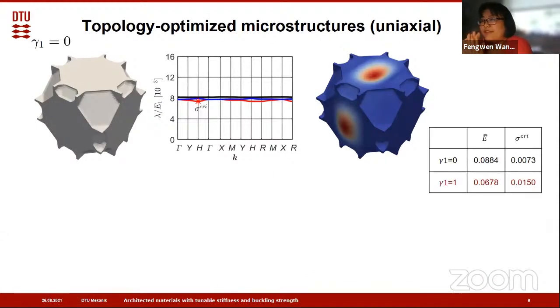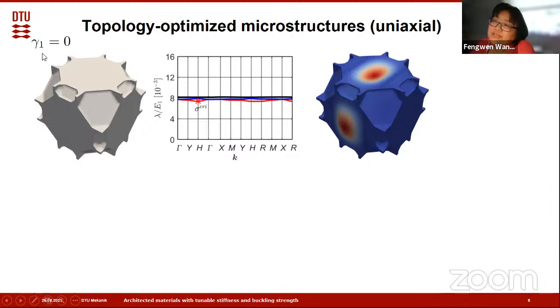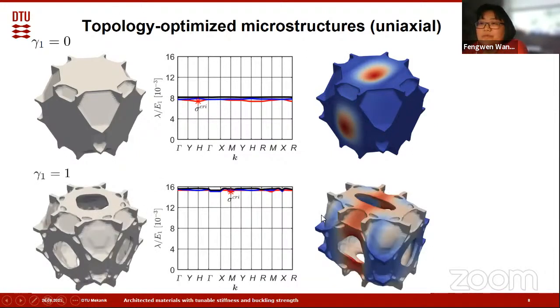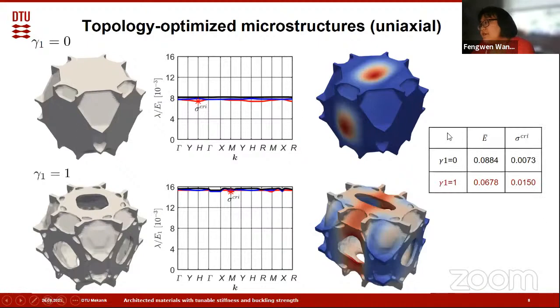Now we know our optimization formulation works. We will focus on designing a material class with tunable properties under uniaxial compression. As a first case, we set gamma equal to zero, which means we try to maximize the Young's modulus of the material. This is the result we get. This is the critical buckling mode. For people who are familiar with material design, they may notice this is actually a suboptimal structure for Young's modulus. The reason we get this structure is that the length scale we imposed is much larger than in the stiffness optimal microstructures, as shown in reference one. In the second case, we try to optimize macrostructures to maximize the buckling strength by setting gamma equal to 1. This is the result we get. This is the corresponding material properties. We can see this material has much better buckling strength at a small cost of the Young's modulus.